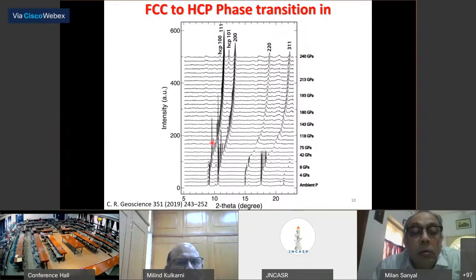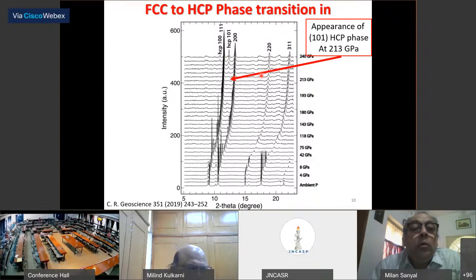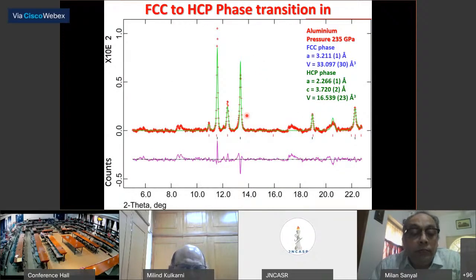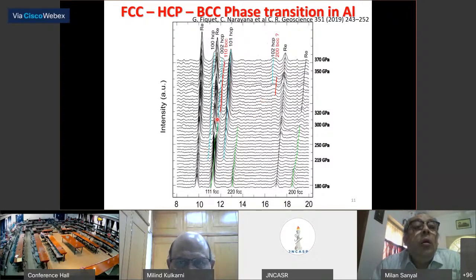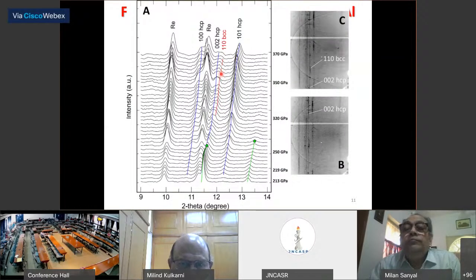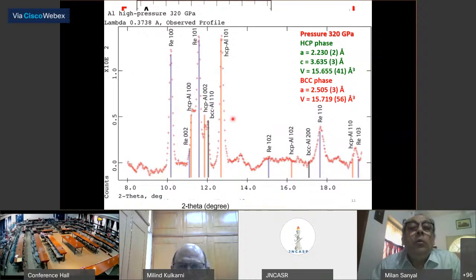experiments. Here is an experiment we have done on aluminum, to just show you how beautifully we can get only aluminum and no other peaks coming in if the size of the gasket is very high. And then we go on to see the HCP phase evolving, which was seen earlier. But when you go to higher pressures, we suddenly see the evolution of the BCC phase in this system. And you can see that the BCC phase is coming along with the HCP, but now you can see that the peak is actually dominated by the gasket material as well in the system. So that is the problem when you have